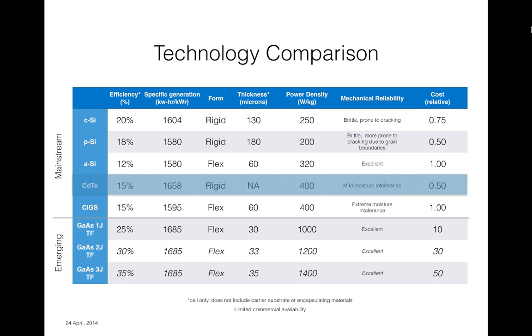Now there is a thin film version of crystalline silicon, which I've noted there. It's called amorphous silicon, and it's denoted as a-Si. And it is a material that is also silicon. It's not monocrystalline. It's amorphous. It's a random crystal structure, and because of that, it has much lower efficiency. The best cells produced to date are about 12%. So I'm giving them the benefit commercially. Commercially available amorphous silicons are really about 10%. But if we look at really efficient cells, well crafted, you could probably get to 12%. And the cells are much thinner, 60 microns.